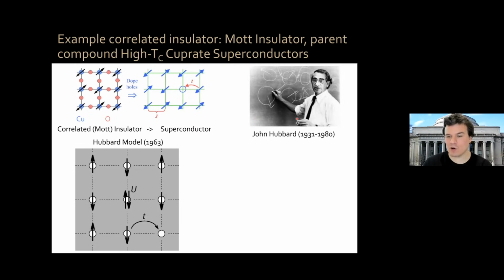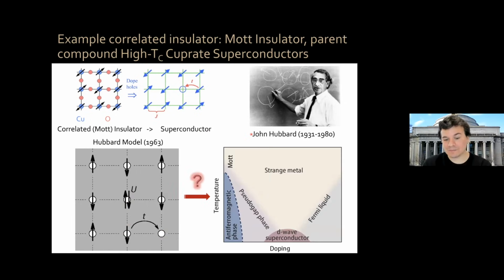Now, we believe that the essential physics contained in the superconductivity in the high temperature cuprate superconductors is described by this model called the Hubbard model, where you take into account the charging energy or repulsion of putting 2 electrons in one site. And you take into account also the tunneling between sites, when one of those sites is empty. But now, I say that we believe that this contains the essential physics of high temperature cuprate superconductors, because this model, the Hubbard model, even in the simplest of implementations, cannot be solved theoretically, despite more than 35 years of intensive research on this model. So how do we go from here to here is still a mystery.